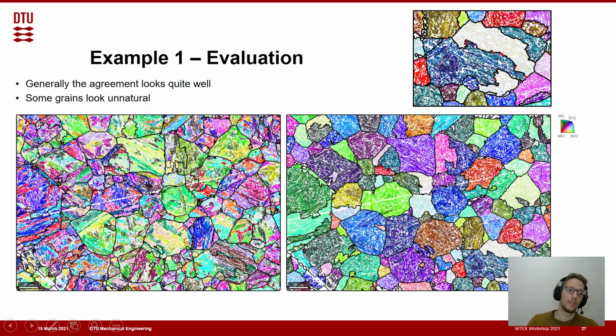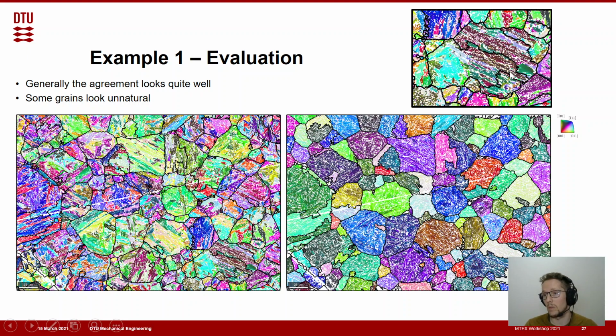And yeah, the next speaker, Tuomo Nyyssönen, will talk about this issue that we have in parent grain reconstructions when we have annealing twins in austenite. And this is likely the case right here. Because if you look at what the martensite orientations have been, it's very unlikely that this boundary here goes through an area where we have almost the exact same variant all the way around. And it's maybe more likely that the boundary should go here, or maybe that all of them are part of one grain. So yeah, this is something the next speaker will go a little bit into.